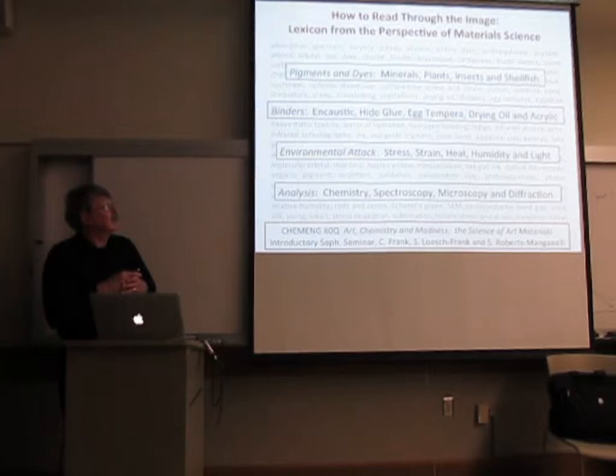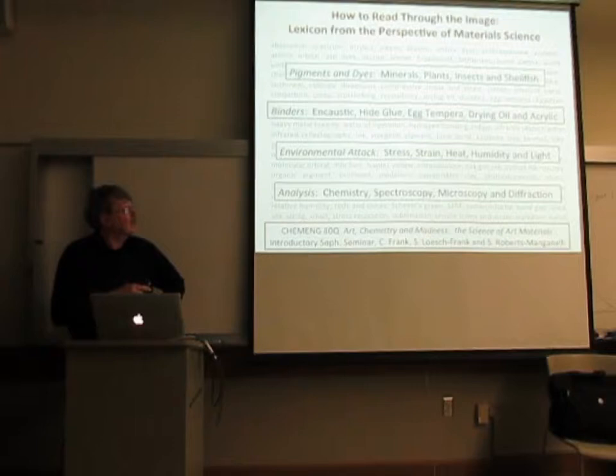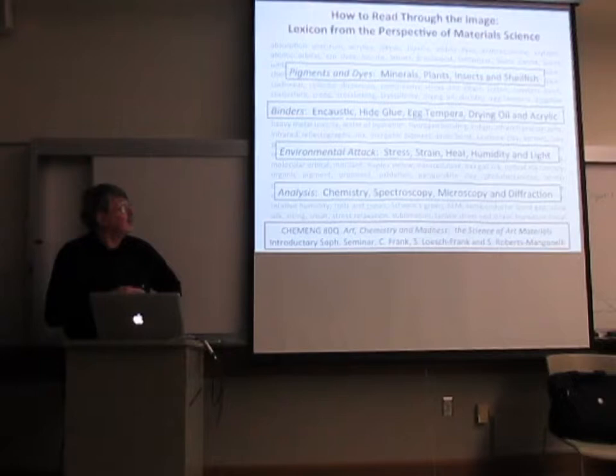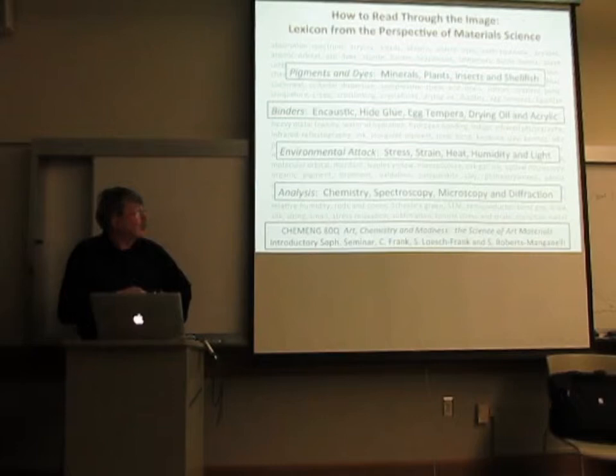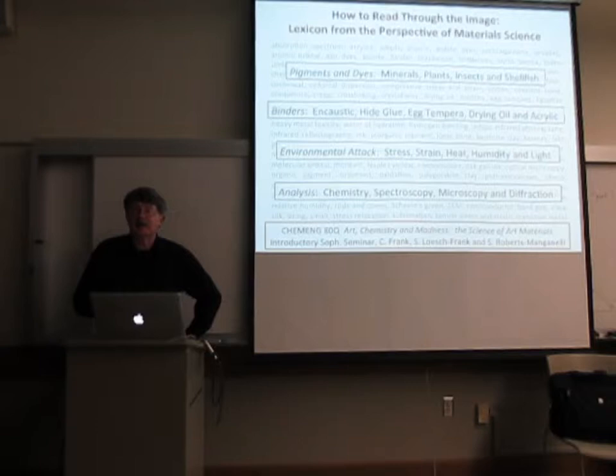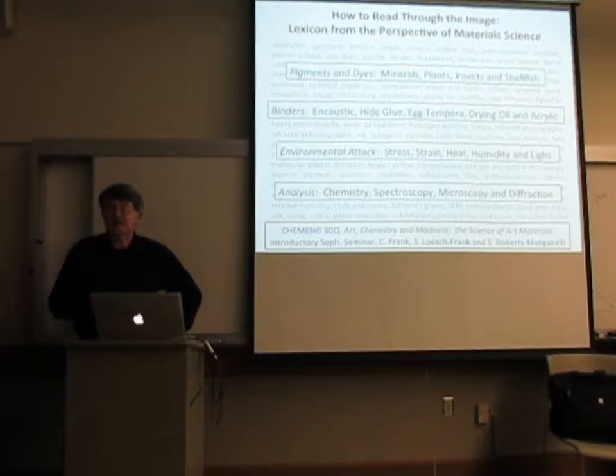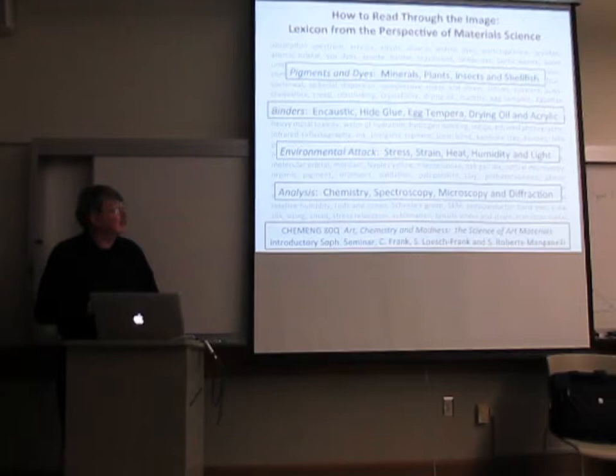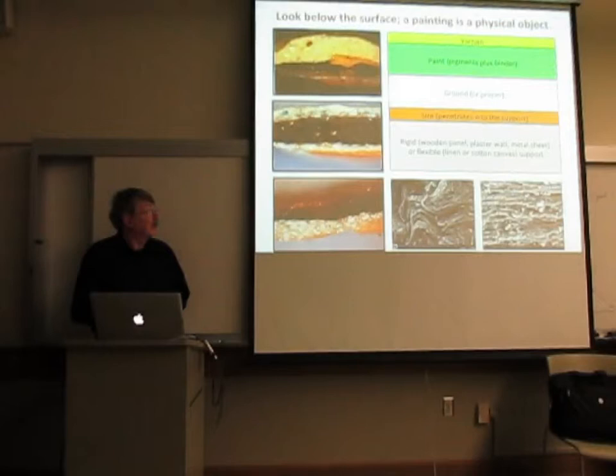I'm interested in a wide variety of materials, but particularly pigments. Historically, pigments have come from all sorts of sources — some unusual, like shellfish. You have to hold pigments together with a binder. Historically these have included encaustic, basically a wax-like substance, hide glue, egg tempera, drying oil, and modern acrylics. This combination of binder plus pigment, when put on a wall, panel, or canvas, is subject to various environmental stresses — heat, humidity, and light.